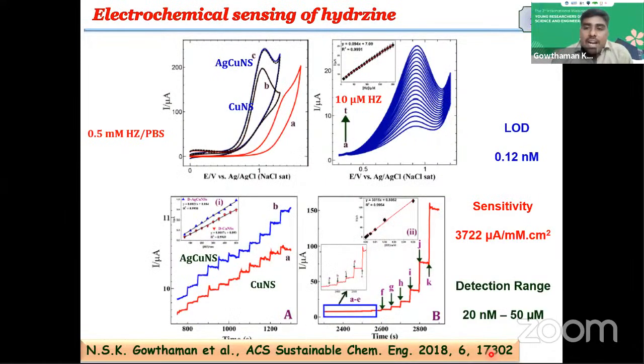And then the modified electrode is utilized for hydrazine determination. Here we already discussed the copper nanostructures for hydrazine detection. Over the copper nanostructures, silver copper bimetallic nanostructures exhibited higher electrocatalytic activity towards hydrazine with a limit of detection of 0.12 nanomolar with a superior sensitivity of 3722 microampere per millimolar per centimeter square, with the detection range of 20 nanomolar to 50 micromolar. This paper was published in ACS Sustainable Chemistry in the year 2018.